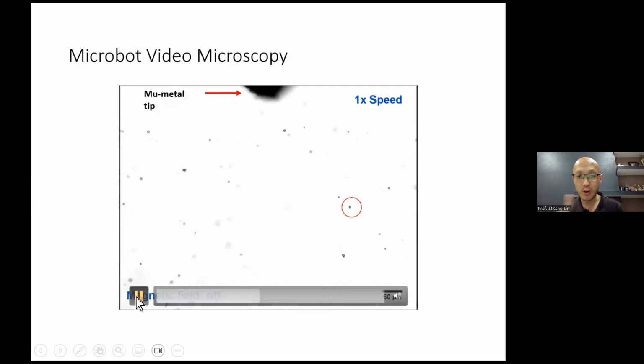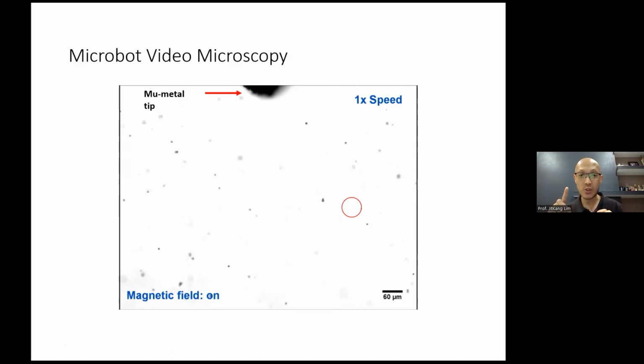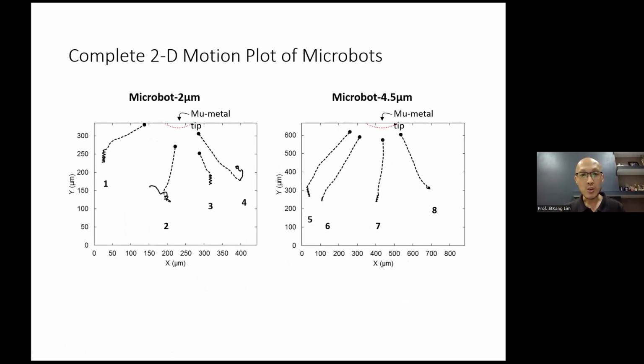Pay attention: before the magnetic field is turned on, it's just going through helical motion. And after we turn on the field, the whole construct moves over to the mu-metal tips, which is not surprising because we imparted magnetic properties onto the cell. All right. If we track the motion path of the whole construct, we tracked quite a number of them, and eventually we could decompose the motion pathway into two parts. The red circle one is before the magnetic field is turned on, and the broken line is after the magnetic field is turned on. The broken line just shows the particles responding to the magnetic field, like we expected, and moving over toward the mu-metal tips, or toward the magnetic field. And interestingly, the cell actually goes through a certain kind of helical motion. Every one of them goes through helical motion.